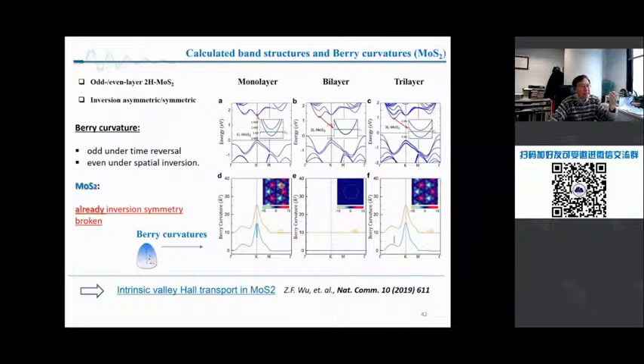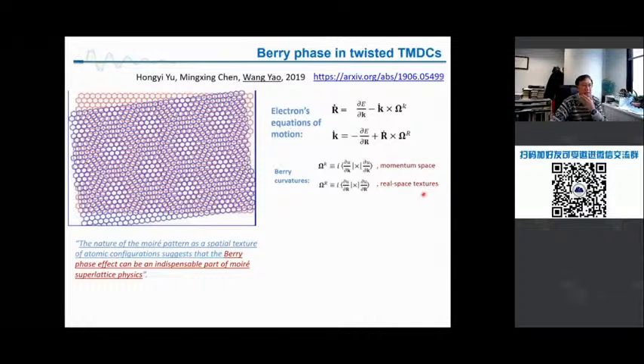And previously we calculated, let's say, the monolayer. You see a pretty strong Berry curvature because there's no inversion symmetry, and in bilayer inversion symmetry is restored, and you see there's no Berry curvature. Trilayer, see again, you detect the intrinsic properties of Hall effect. Twisted material: this is the equation written by Professor Yao Wang from Hong Kong University. They explain it that way.